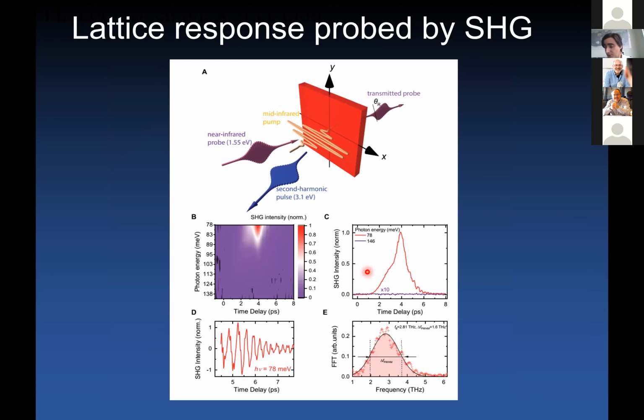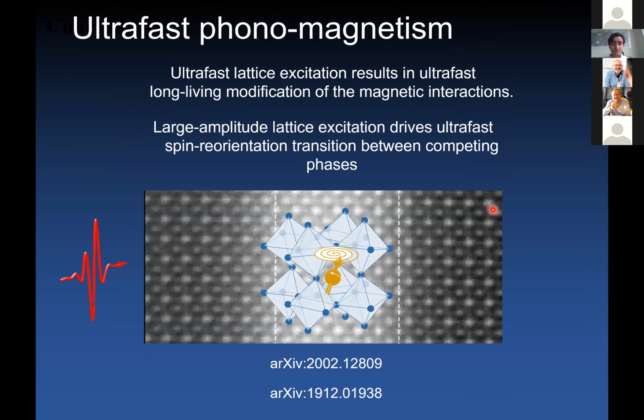What is the lattice doing across this phase transition? We do measure second harmonic generation as a probe of the crystal lattice dynamics, and we do observe structural dynamics associated with this transition, which indicate that a Raman mode mixed with a strain wave is present in our system. So, consistently with the lanthanum aluminate data that I showed you before.